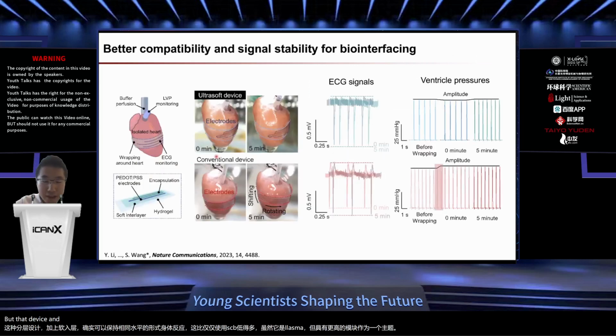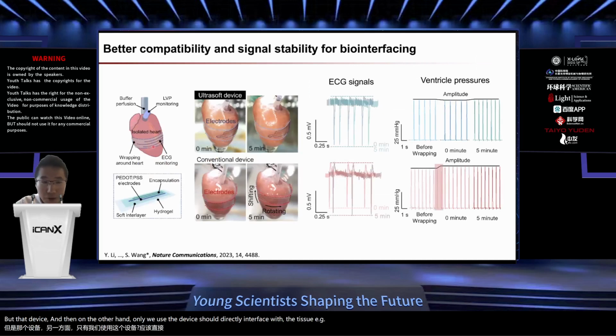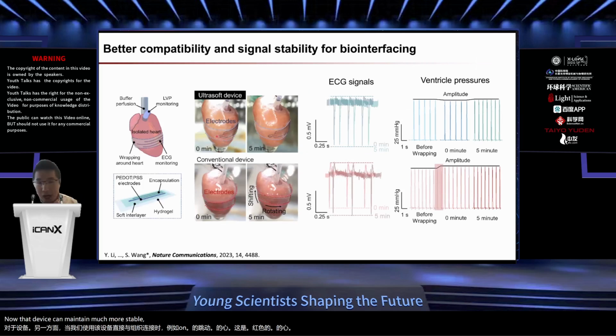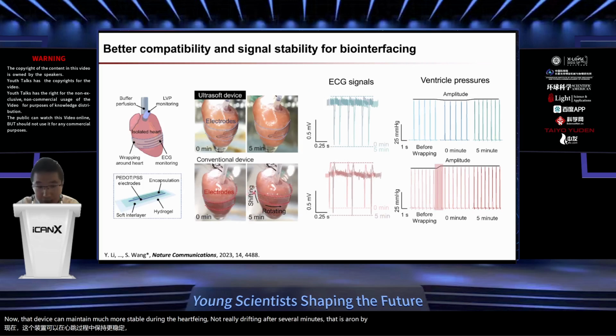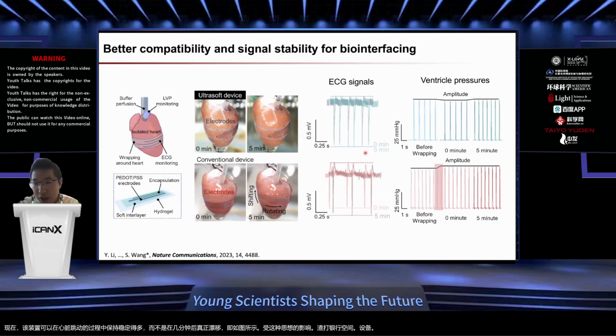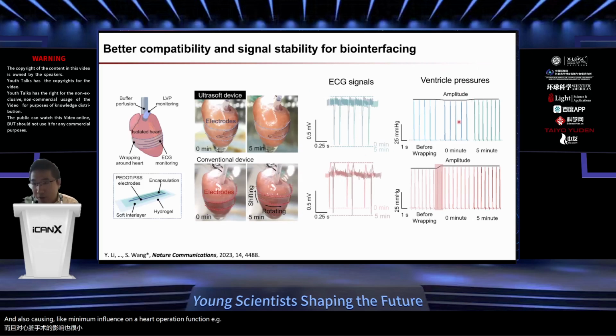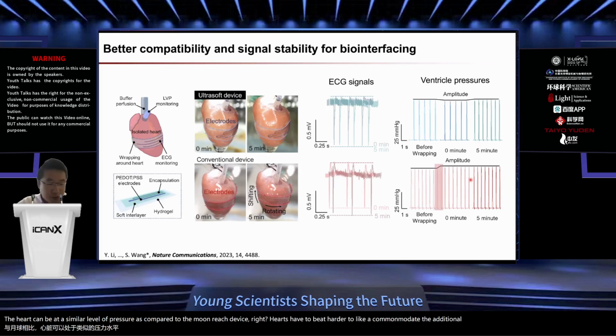And then, on the other hand, when we use the device to directly interface with the tissue, for example on the beating heart, this is an isolated heart, now the device can remain much more stable during the heart beating, not really drifting after several minutes. That is as shown by this SEBS-based device, and it also causes minimal influence on the heart's function. For example, for the ventricle pressure, the heart can beat at a similar level of pressure as compared to the more rigid device, where the heart has to beat harder to accommodate the additional mechanical force.